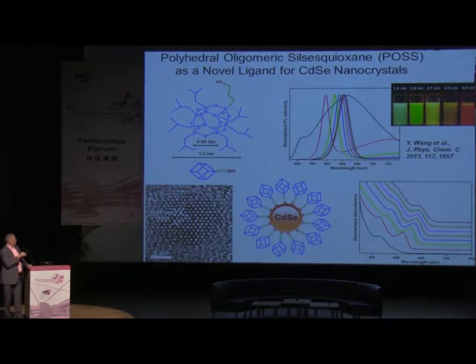I mentioned that ligands on nanocrystals are important, and this is still an ongoing topic for research worldwide. Here you can see that we decided to employ this cage-like ligand, which is called polyhedral oligomeric silsesquioxane, to synthesize cadmium selenide quantum dots in that case. Again, we tune the emission by size of the core. And into this particular cage, we can, for example, place some ions or some small molecules. The emission may be quenched or enhanced, depending on the interaction with the light-emitting core, and this is a sensor then. Or we can process this kind of coated cadmium selenide nanocrystals into very high quality thin films, because these are building blocks for silica gels.